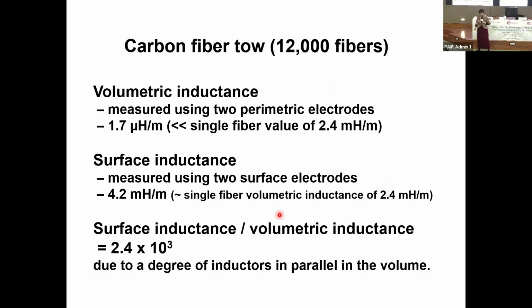And here are the results for the carbon fiber tow. The volumetric inductance is small, as I've already mentioned, 1.7 microhenry per meter, but the surface inductance is 4.2 millihenry per meter, and it's kind of close to the single fiber volumetric inductance of 2.4 millihenry per meter. And so the ratio of the surface inductance to the volumetric inductance is 2.4 times 10 to the 3, and that is due to a degree of inductors in parallel in the volume.